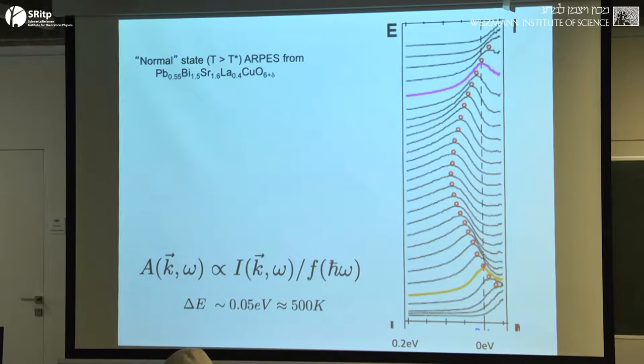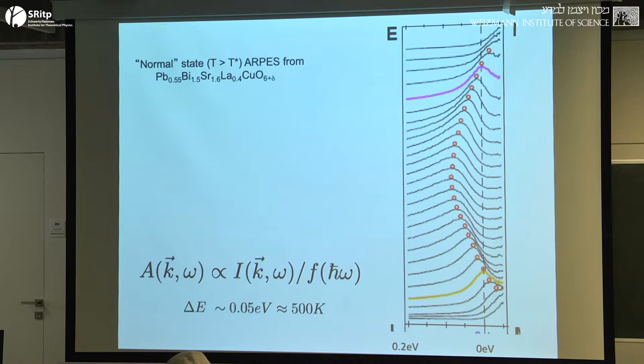So the widths of these peaks are broad compared to the temperature, whereas we're in a regime where the resistivity is linear in temperature, so some current scattering rate is maybe a few times smaller than this quasiparticle scattering rate.